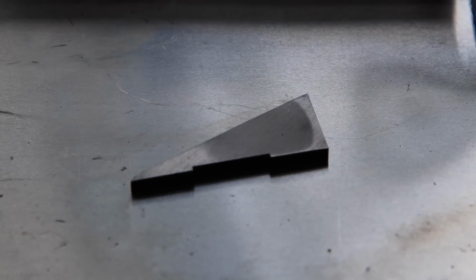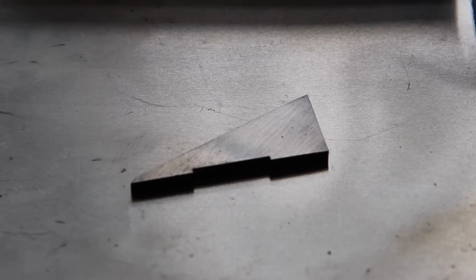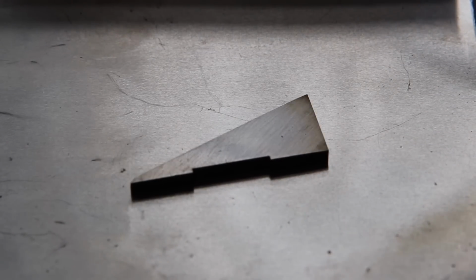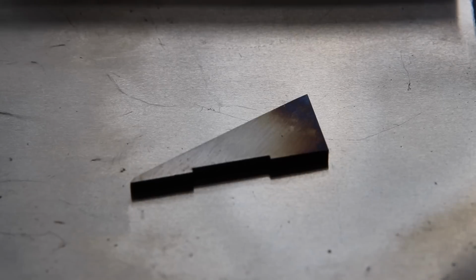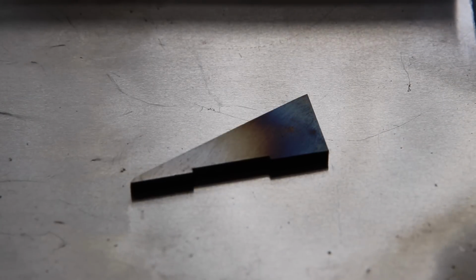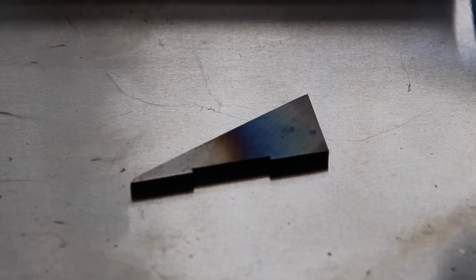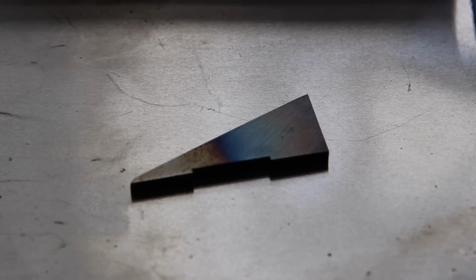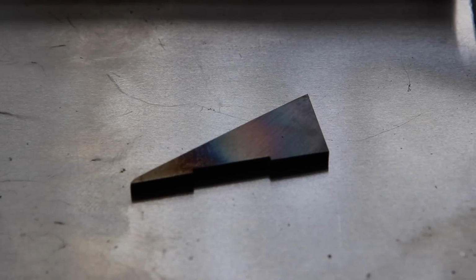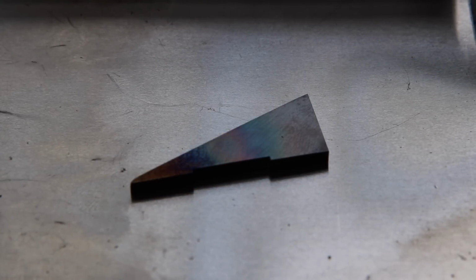I've heat treated both parts and now I want to temper them. It's a little difficult to see on the video here, the lighting's not very good, but I'm heating the part from one end using a blowtorch, and I'm just waiting for that colour to start changing. And here it goes. You can see it starting to change from that kind of straw colour to a blue, and for that colour graduation to start chasing its way down towards the tip of the tool, because I'm heating it from one end. And yeah, we just want to get that straw colour onto the tip.